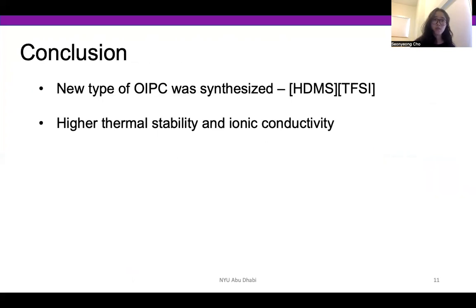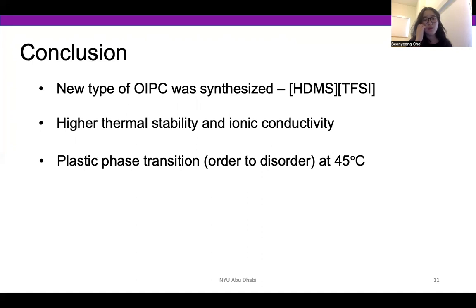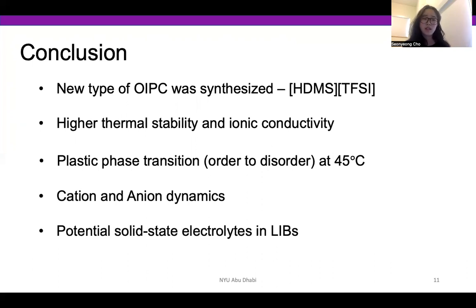interactions. So to conclude, in this research project, a new type of OIPC was synthesized, namely HDMS and TFSI, and higher thermal stability and ionic conductivity was observed compared to many other OIPCs that have been reported in literature. And the plastic phase transition, order to disorder, has been observed at 45 degrees Celsius, and the cation and anion dynamics was studied using solid state NMR. And these analytical techniques and the results show the potential of using this new material, HDMS TFSI, as solid state